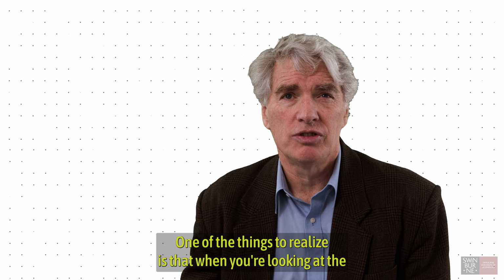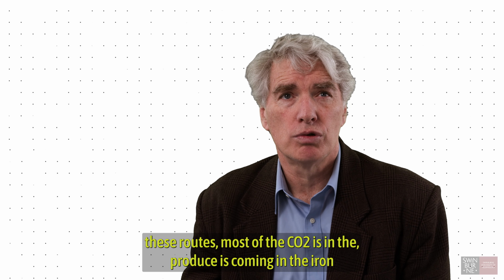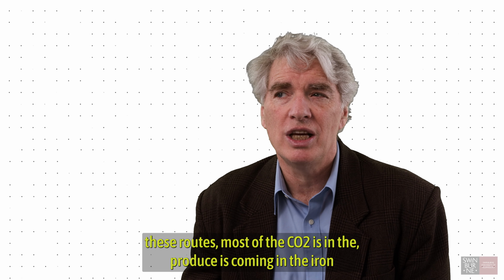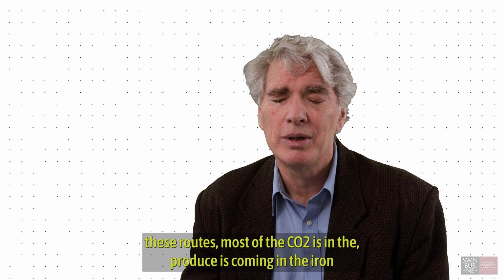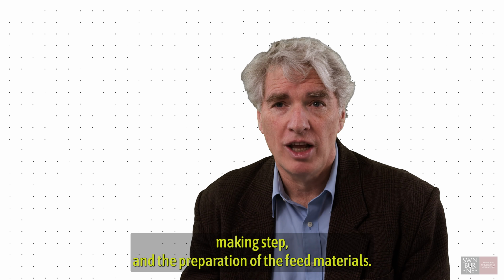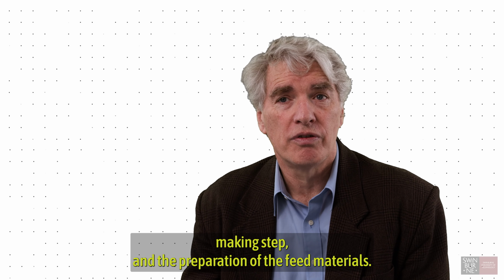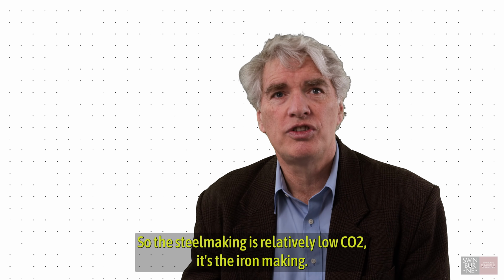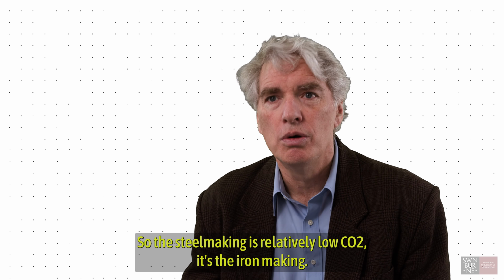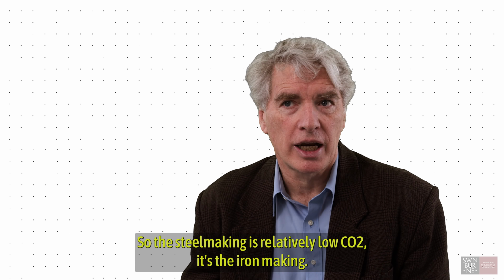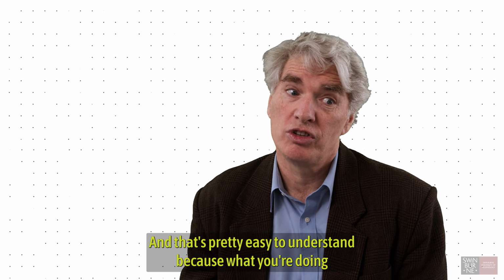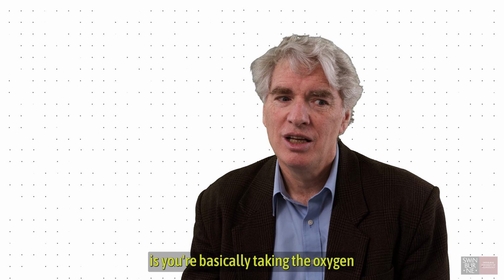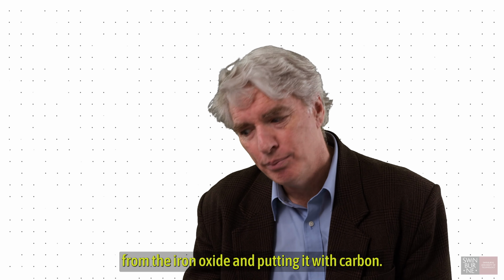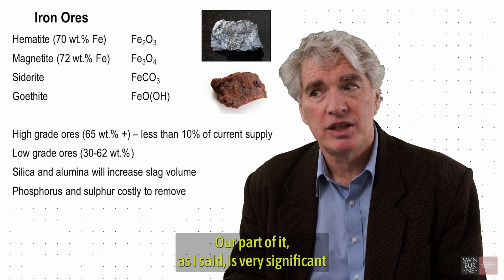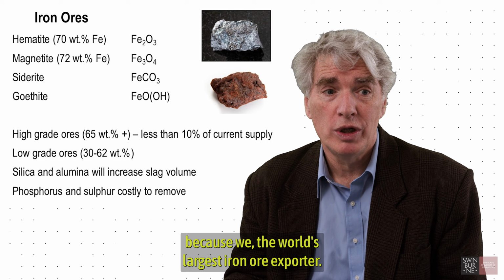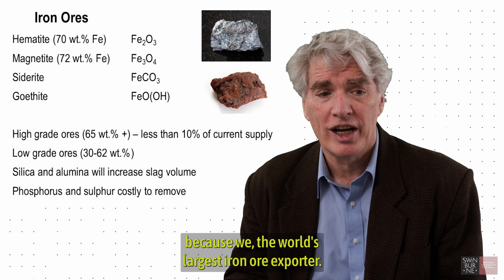One of the things to realize is that when you're looking at these routes, most of the CO2 is in the iron produced, coming in the iron making step and the preparation of the feed materials. So the steel making is relatively low CO2. It's the iron making. And that's pretty easy to understand, because what you're doing is you're basically taking the oxygen from the iron oxide and putting it with carbon. Our part of it, as I said, is very significant because we are the world's largest iron ore exporter.